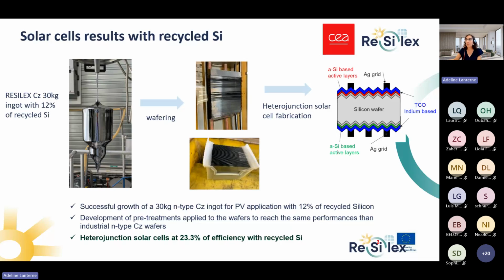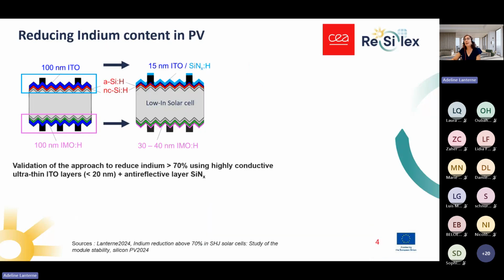So this was the first important proof of concept using this recycled silicon, and also a first step towards a new circular model for silicon in Europe. Now I will present a few results about how we reduce indium content in the project. For that, we worked on several aspects, but here I present only an approach where we reach very high TRL in the project. It's an approach where we reduce the indium containing layer, which is the ITO layer in blue in the cell, and